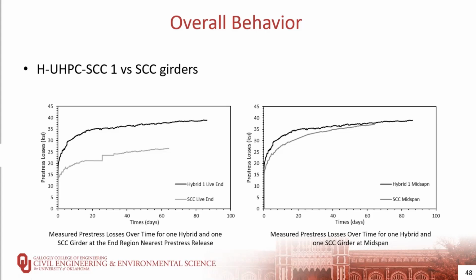Since UHPC has a shorter transfer length, the end region is under greater stress. The black curve shows the greater deformation and losses over time compared to the SCC live end, which suggests the high compressive stress resulted in more creep over time.